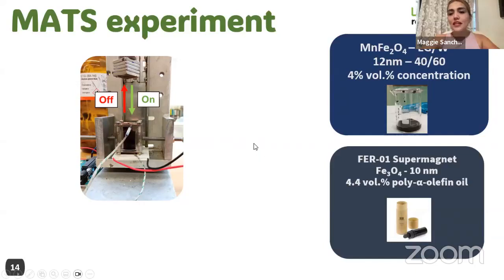So do you have any idea why there's a difference in viscosity or rheological behavior? Do you think one of them is less well dispersed or more agglomerated than the other? Because the concentration is similar, the size is similar. Of course, the solvent is different—one is ethylene glycol, the other is the oil. Do you think it's because of the solvent? In both cases, the particles are well dispersed, and they're also very stable chemically.